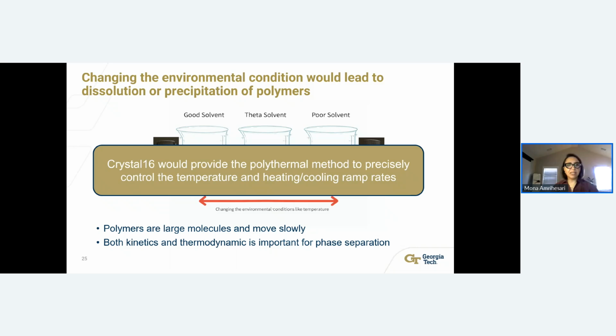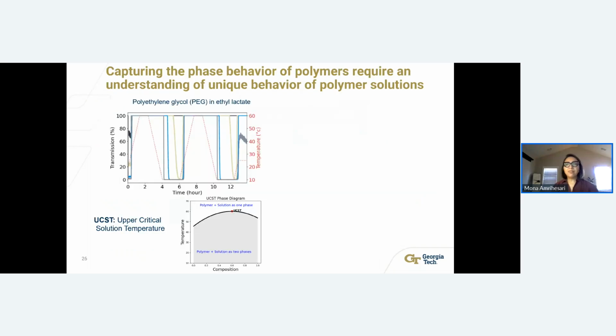So Crystal 16 provides us with this polythermal method to precisely control the temperature and also adjust the heating and cooling ramp rate, because we are dealing with a very large molecule, to screen the changes in polymer solution condition as we are changing its environmental condition. But this task of standardizing a method was specifically challenging because we are not dealing with the same material that has the same solubility profile.